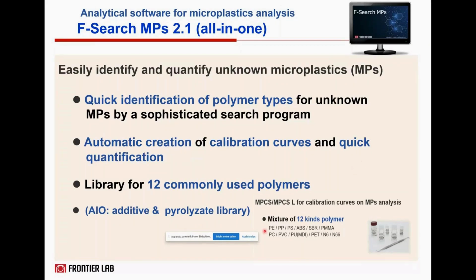And if you order F-Search MPs, then in the package you also find our microplastic calibration kit, which now comes in two versions, the microplastic calibration standard and the microplastic calibration standard L for low amounts of polymers, for the creation of the calibration curve in microplastic analysis. And the types of polymers which are included in the library and in the kit are listed here. And the trick is that we have diluted the polymers in inorganic diluents, either in quartz or in calcium carbonate.